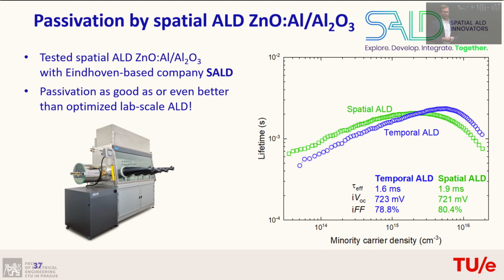So is it then possible to make this using industrial tools? The answer is yes. So in Eindhoven, there's a few companies that have been busy with atomic layer deposition machines now for some years. And this company, SALD, was so nice to try this process on their machines. So we compared basically the lab scale process that you see here as temporal ALD, that is the Eindhoven University result, and then we used a spatial ALD reactor, which is the green data set. We see basically that the results are more or less the same. If you want to be very picky in terms of lifetime, it is a little bit better even. So we might say that it is at least matching the results from the university labs. So if you go for more optimization, it can maybe even be better.